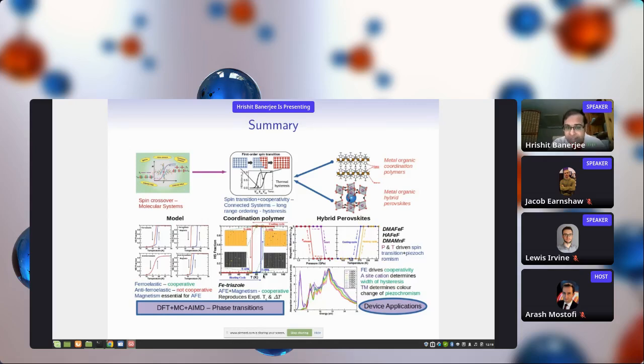And we prove this in a well-studied experimental material of iron triazole, and we can reproduce the TC and delta T. However, we also propose hybrid perovskites as the new materials in which spin crossover and spin transitions may be studied, and we can show that both pressure and temperature driven spin transitions and piezochromism exist in case of hybrid perovskites. We study this with DFT plus Monte Carlo and AIMD, and this is a very useful tool for studying phase transitions in these kinds of materials.